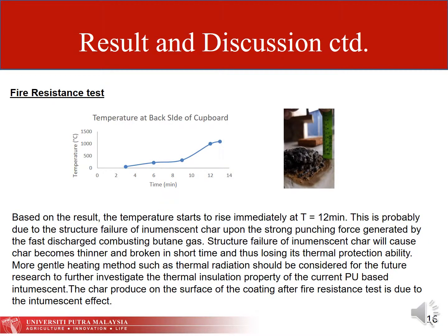For the fire resistance test, based on the result, the temperature starts to rise immediately at 12 minutes. This is probably due to the structure failure of the intumescent char upon the strong punching force generated by the fast discharge of combusting butane gas. Structure failure of the intumescent char will cause the char to become thinner and broken in a short time, thus losing its thermal protection ability. More gentle heating methods such as thermal radiation should be considered for future research to further investigate the thermal insulation property of the current PU-based intumescent. The char produced on the surface of the coating after the resistance test is due to the intumescent effect.